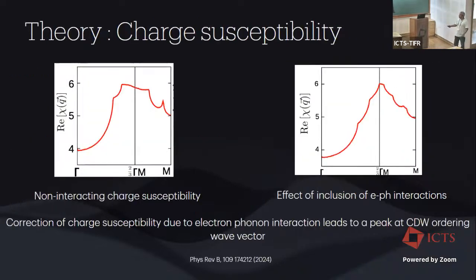Now, if you look at the charge susceptibility for the system, one of the things that comes out is that if you just look at it from a nesting-driven picture, you do not get a maximum peak in the charge susceptibility at the CDW wave vector. The CDW wave vector lies around 2/3 ΓM. The peak is actually shifted from it. However, very similar to the story of bulk NbSe2, if you include the effect of electron-phonon interactions in your system, then the peak shifts right onto 2/3 ΓM. In fact, this is still calculated as a density-density correlation from the tight binding model. If you do more critical DFT calculations, it actually even shows that the CDW peak enhancement is much stronger than what you find in the bulk system.